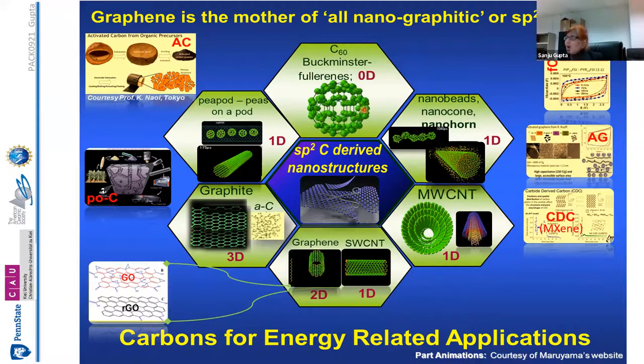Along with the activated carbon, we have studied activated graphene. Then we have functionalized carbon nanotubes, depending upon the functionality, be it oxygenated groups, nitrogenated groups, or even sulfonated groups. They showed an enhancement in their charge storage capacity. Then there's a whole family of layered materials, as you probably have heard, graphene and transition metal dichalcogenides; these are layered systems. That's the beginning of the 2D systems. Then there's another layered family, what we call CDC, or carbide derived carbon, and also MXenes. We have studied a little bit of MXene as well in collaboration with China. So that is what I'm going to discuss.